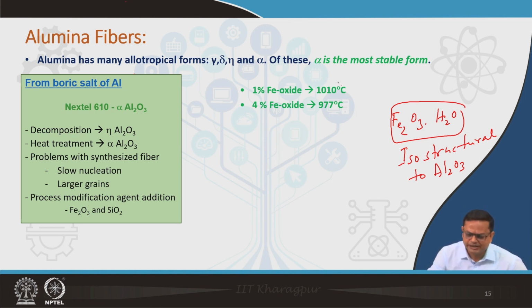Okay. Depending upon how much iron oxide you used, you can see here the temperature goes from 1010 degrees Celsius to 977 degrees. So, there is a decrease in temperature also in the process. Okay. So, that is the basic technique of alumina fiber synthesis, where you start with a boric salt, and then you get eta Al2O3, and then you go for heat treatment to get alpha Al2O3, and during that you use a nucleating agent, either Fe2O3 or SiO2, and then ultimately you get very fine grains of Al2O3 in the process.